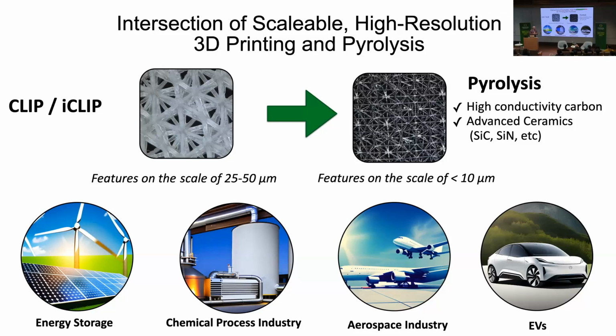30% of the carbon dioxide emitted in the United States comes from the chemical industry, from burning fossil fuels to drive endothermic reactions. Everybody wants to electrify the chemical industry like they've electrified the transportation industry. So this is designing new ways of heating electrically, and the most energy efficient way of doing that is inductive heating. So these are new silicon carbide based systems and flow reactors integrated with heating systems. So we're really excited about this new intersection of pyrolysis with 3D printing, opening up entire new fields in a whole bunch of areas, and that's good. You'll see a lot more coming from our group in that area.